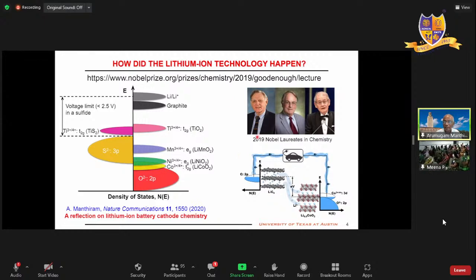So he was very familiar with all the oxides, their structure, what they do, bonding, covalent bonding, ionic bonding. And he also knew how the energy levels of some of these things change. So very simple. Now it may look simple. He knew, okay, you have voltage limitation and you have a problem using lithium metal. I know something, lithium cobalt oxide, that has a layered structure like here. And also, if I go to an oxide instead of a sulfide, the oxygen 2p band lies at a lower energy than the sulfide 3p band. Therefore, I will not have this kind of block.